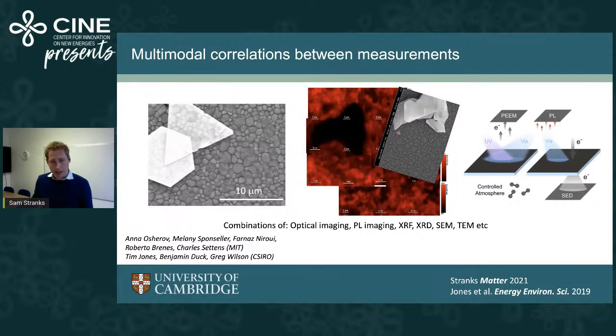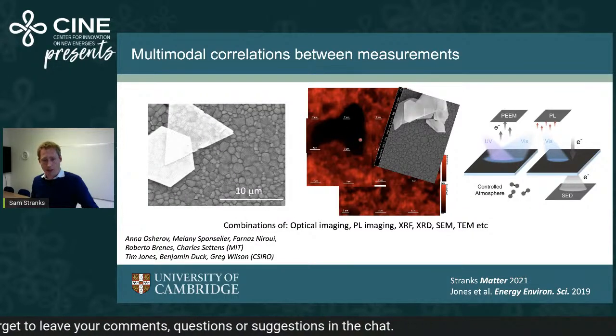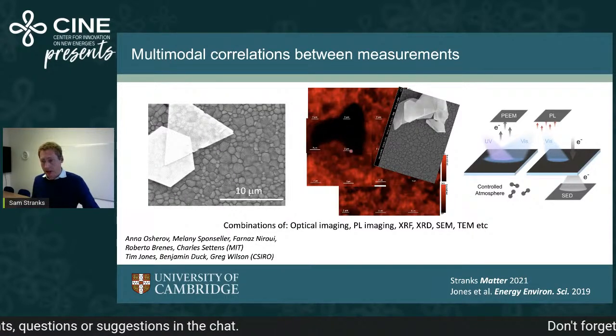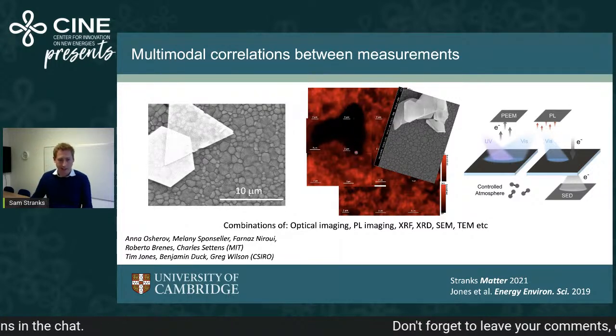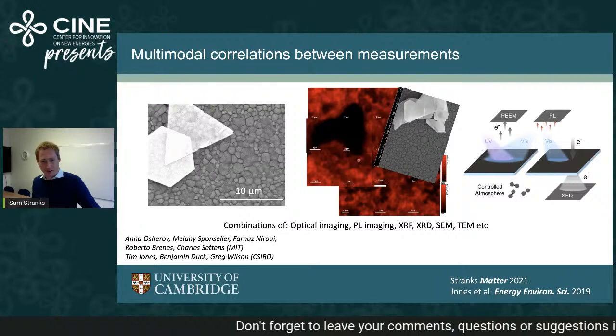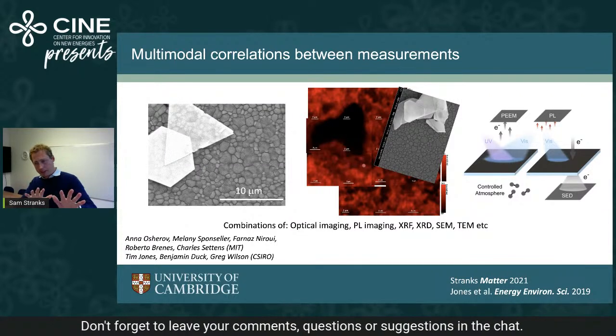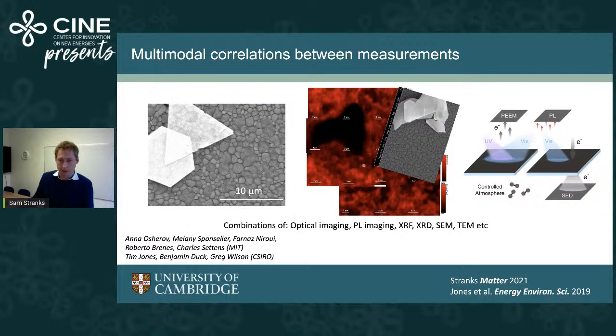This is an example of an SEM image around one of these clusters, and then this is what it looks like in the photoluminescence map. And again, we can overlay these and extract information. I particularly like this one because it looks like a map of Australia, which is where I'm from. You can even see Tasmania off the south coast here as well. In fact, we use a combination of different measurements to make sure we're very precise. I'm going to show you some examples where we do measurements with photoemission microscopy, photoluminescence, and also probing with electrons on the same area to really try to unveil what's happening in these materials.